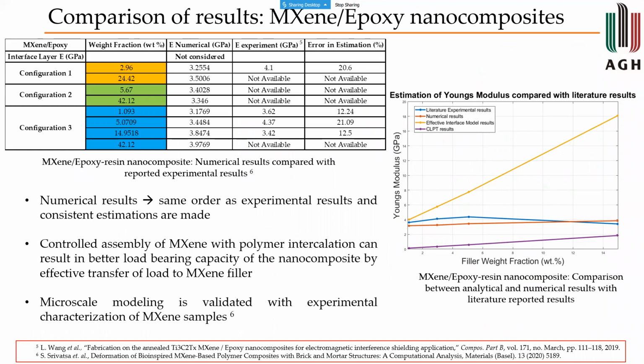This was so that the overall results could be matched with some experimental outcomes that we had. We found that the numerical models were performing better than the analytical models which are used for nanocomposites, but were not in great agreement. The order of magnitude would be the same, but the error of estimation would be very high. The reasons for this are also linked to the chemistry of the material and how it reacts with the polymer. The results that you see are for MXene epoxy, where you have some amount of agreement with the experimental results that have been published.